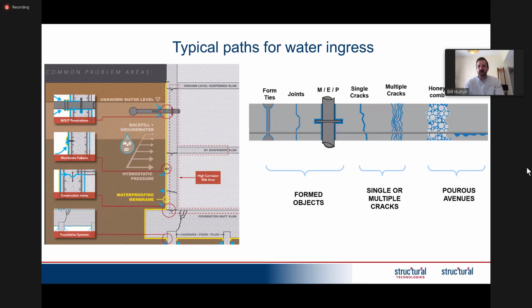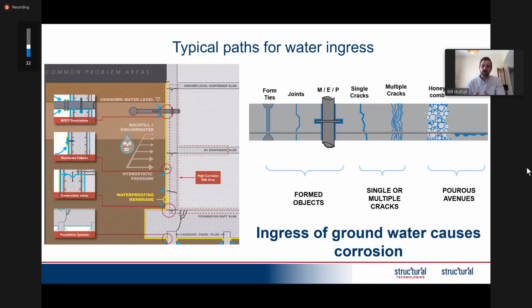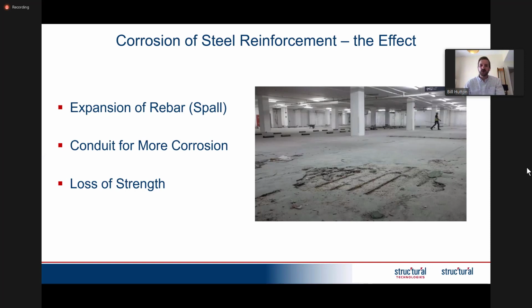And as Morty discussed in detail yesterday, groundwater coming into a building is one problem, but really the bigger picture is that this groundwater contains salt, which causes the steel to corrode. So I'm not going to go into detail on the mechanisms because that was discussed yesterday, but once the chlorides get into the concrete, they cause the steel to corrode. Corrosion product is very expansive, so it means it can occupy 10 times more space than the steel, so it grows on the steel, puts pressure on the cover, and can damage the concrete, which can end up resulting in a loss of strength for the structure.